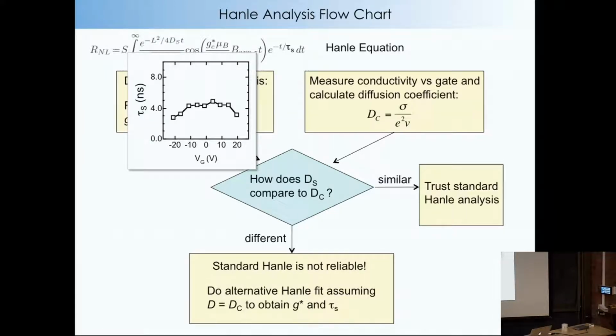So this effect is not happening in those samples, because D_S and D_C are pretty similar. I didn't mention it before because it wouldn't have made any sense back then. But all those previous ones are fine. There are different ways you could generate an enhanced G star. Van Wees saw that localized states can generate an enhanced G star, and he saw that on silicon carbide graphene systems. For us, we're seeing it from the exchange field, essentially.